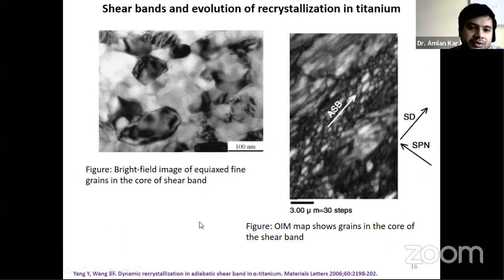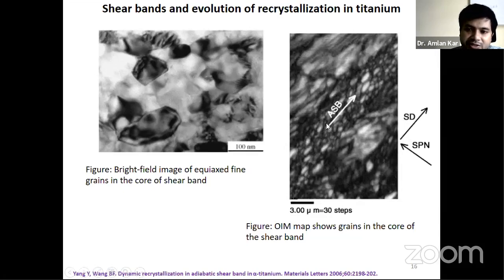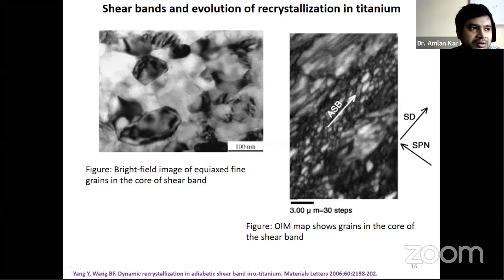There are some examples where people have also observed adiabatic shear bands. In the adiabatic shear band, people have observed recrystallized grains. You can see there is a very fine recrystallized grain, and these are the deformed grains, but they are not subjected to recrystallization because it is an adiabatic deformation process. The flow stress in the adiabatic shear band is very, very low, and therefore it leads to fracture and a higher amount of shear deformation.